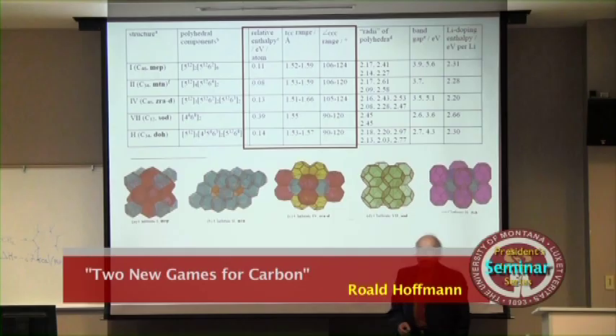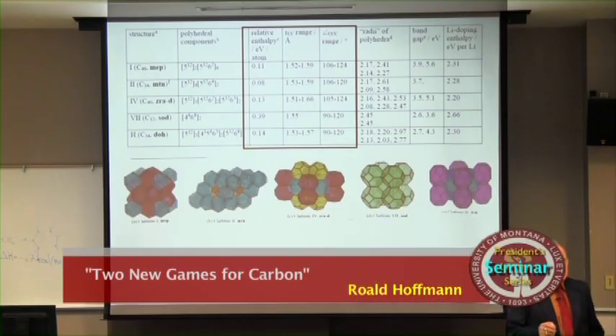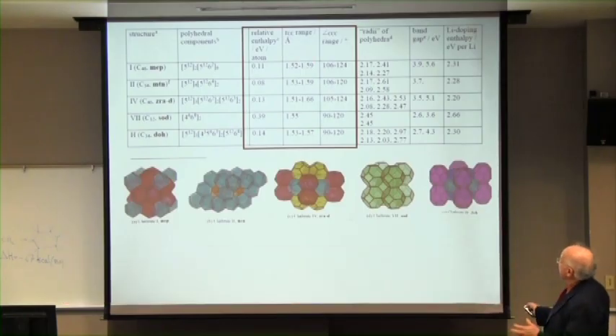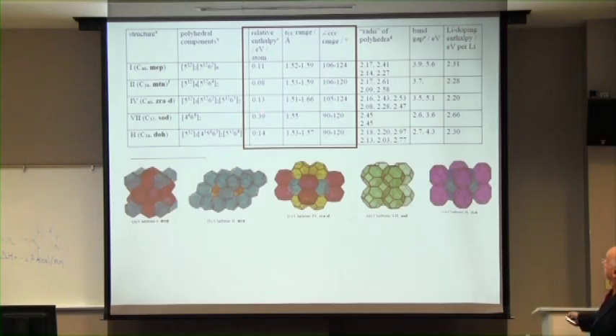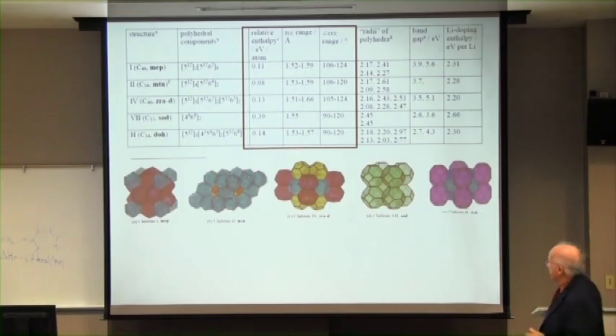Okay. So why are these things so close to diamond? The reason is that the clathrate structure does not require much distortion. Here is the range over all the angles in all the polyhedra and all the distances. And you see that these are distances, with the exception of one distance in clathrate 4, they are all pretty close to 1.53. And the angles, there are some 120-degree angles and some a little bigger, but not much, not terribly strained as these things go. So that's the reason why these are unstable, but still not so unstable.